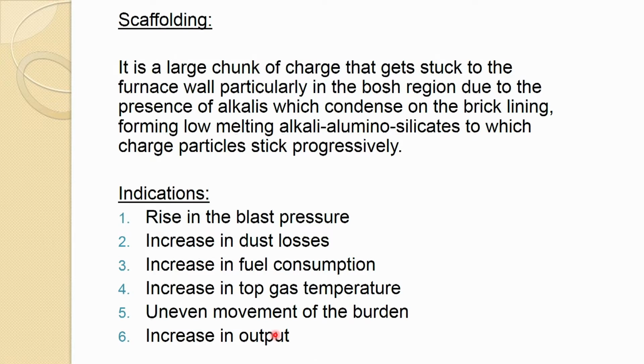So, one important irregularity is scaffolding. It is a large chunk of charge that gets stuck to the furnace wall, particularly in the bosh region, due to the presence of alkali, which condenses on the brick lining, forming a low melting alkali aluminosilicate, to which charged particles stick progressively. So, this is mostly caused by the presence of alkalis.